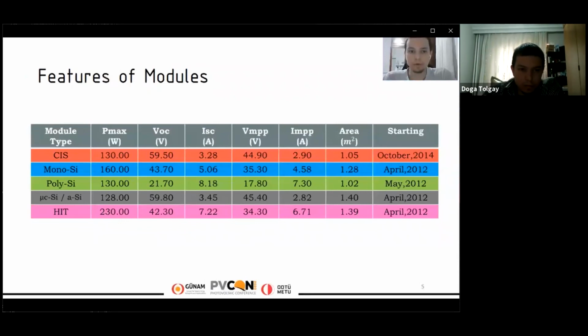We have used 5 different modules. These modules are the CIS, the monocrystalline silicon, the polycrystalline silicon, the micromorph-based amorphous silicon, and the HIT. The CIS module has 130 watts and it is active since October 2014. The monocrystalline silicon module supplies 160 watts and it is active from April 2012. The polycrystalline silicon is active since May 2012 and it supplies 130 watts, whereas the microcrystalline silicon and amorphous silicon tandem structured solar module provides 128 watts and it is active since April 2012. The HIT module provides 230 watts and it is active since April 2012.